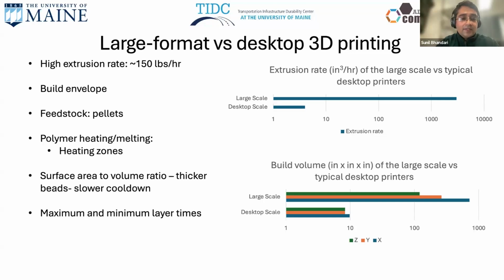Also, the beads extruded in large format 3D printing are bigger, so the surface area to volume ratio is lower. Since the beads are thicker, it takes longer to cool down, which brings us to the idea of layer time. Layer time is the time within which we need to deposit a single layer. If we take too much time, the layer will cool down too much and the layers don't bond well together. If we deposit too fast, the layers have not solidified enough to support the weight of another layer above it. So this limits the extrusion rate.